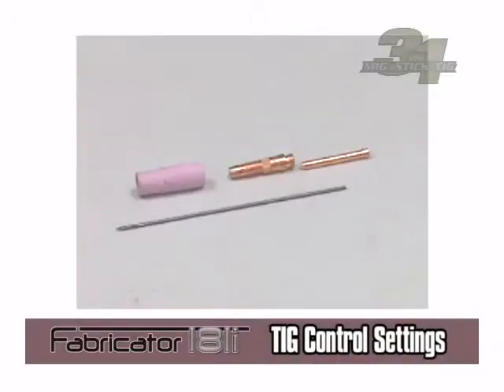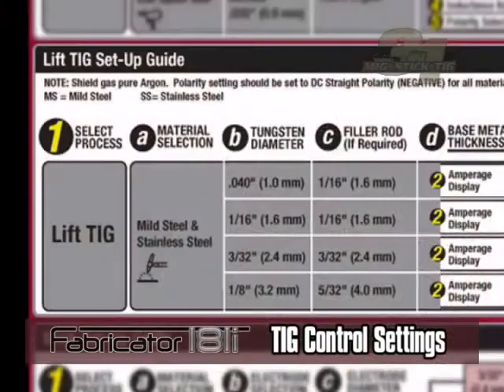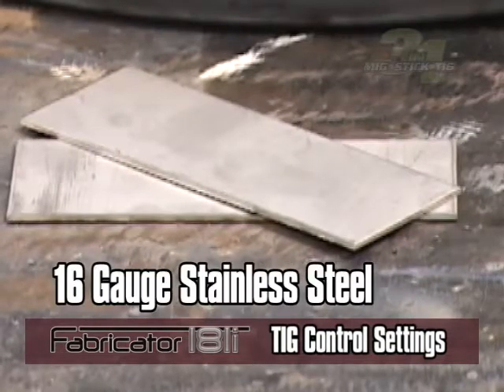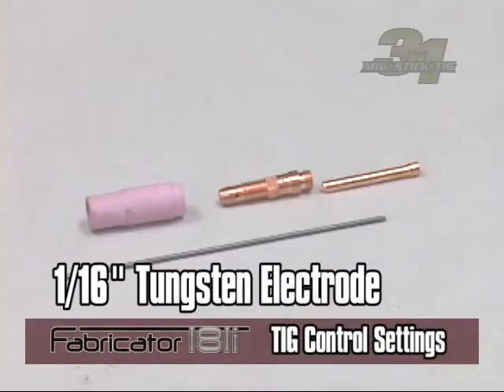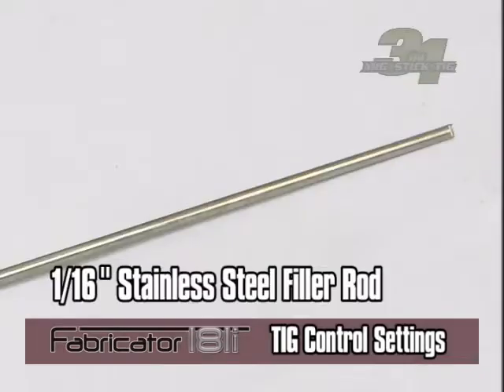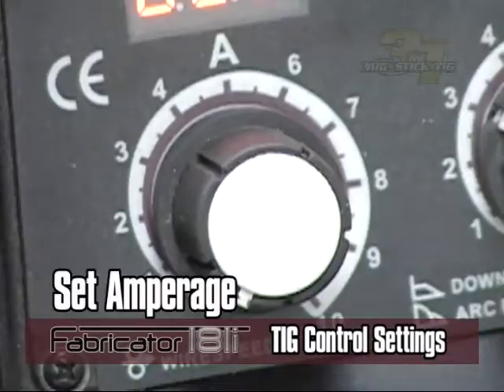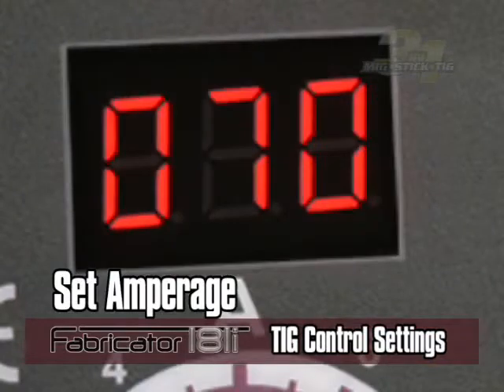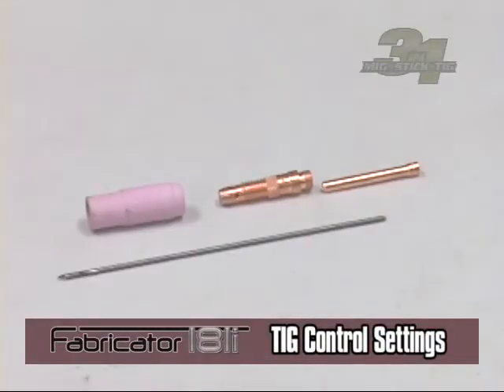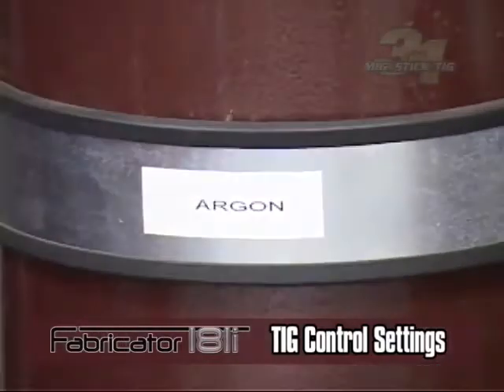TIG welding. Using the setup chart, if you were welding on 16 gauge stainless steel material, you would use a 1/16 tungsten electrode and a 1/16 stainless steel filler rod. Your amperage would be set to 40 to 70 amps. Because your rod is a non-consumable rod, there would be no feed setting. Your shielding gas would be pure argon.